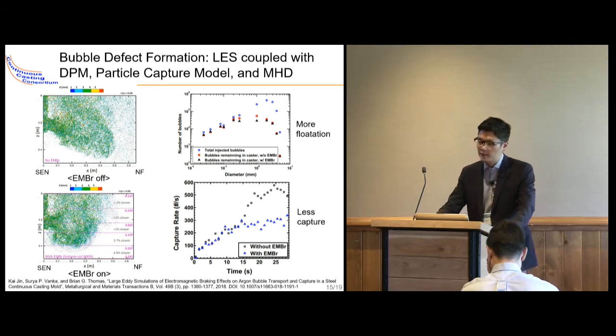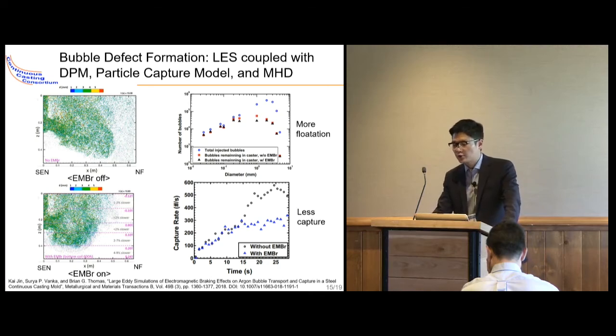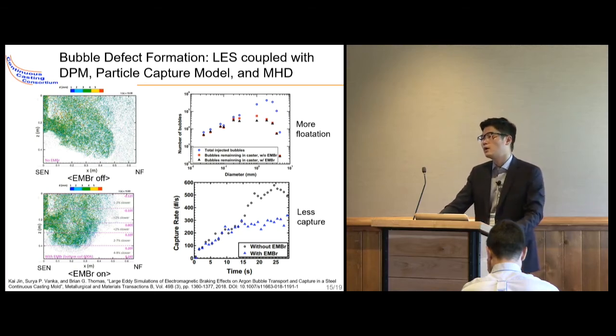Next, we simulated the transport and capture of the bubbles at the steel shell front using the LES coupled with the DPM particle capture model and MHD model. From this model simulation, we can consider the effect of the EMBR on the bubble capture defect formation. The model was validated by comparing with the plant measurement of the real defects in the steel plant.